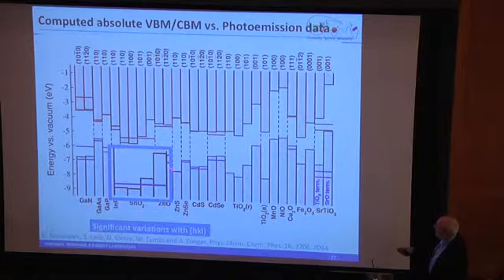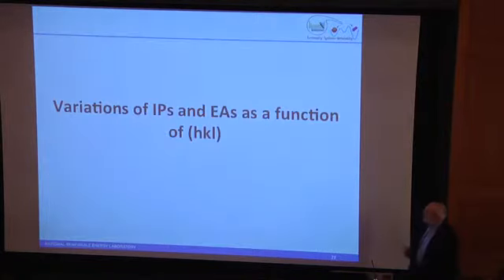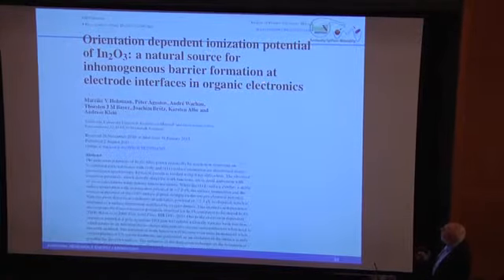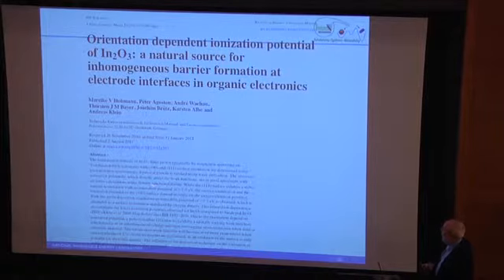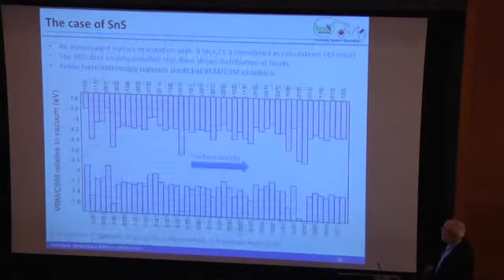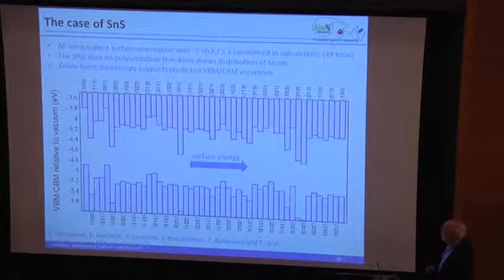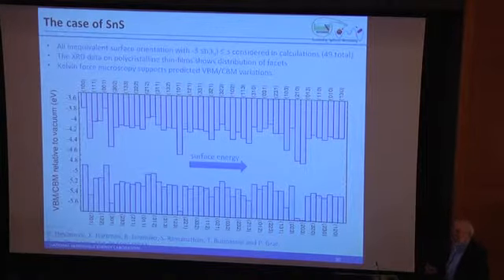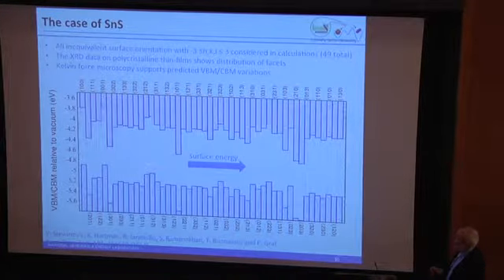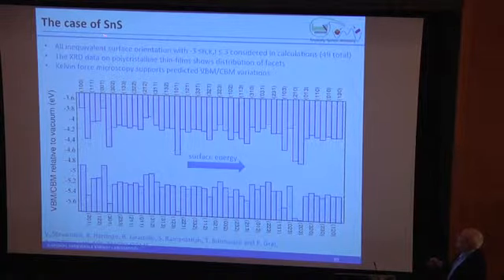But I think that the take-home message here is that the agreements here are actually pretty good between the calculated data and the actually measured photoemission data. So, okay, not bad. There is definitely an orientation dependence. There's been a number of measurements that look at this, and they see the same kind of trends across a wide variety of samples. So what we did is we calculated essentially all of the orientations of tin sulfide.